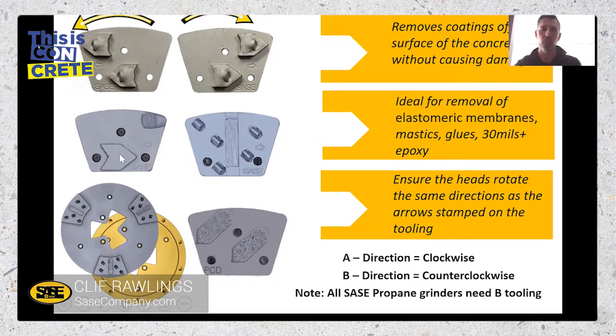The two below it here, this is again the whole full PCD with an arrow, which is basically kind of like a wear bar to some aspect. It keeps this one tooth, if you will, from digging too aggressively and gives it some ability to flatten out a little bit. So that's why you have this. And this is basically just a 30-40 grit arrow seg that's brazed along with a full PCD. Now this is going to be your most aggressive. A full PCD like that is going to be the most aggressive. This is sort of medium aggressiveness, and then this is less aggressive than the other two.